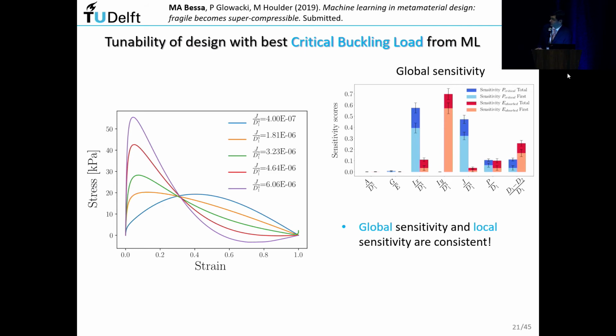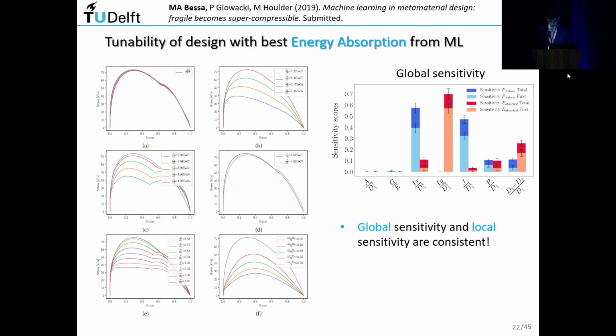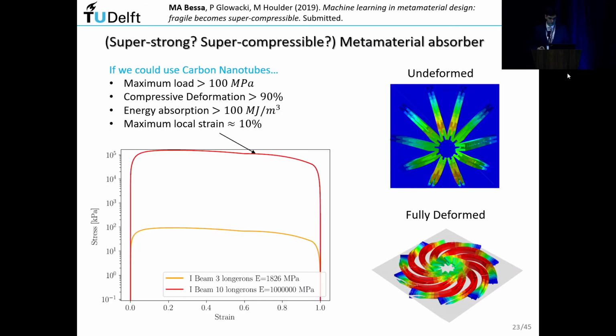You see here that it says that it's very sensitive, the buckling load, to the torsion constant, but not the energy absorption, which is exactly what these plots show afterwards as well. Okay, so there's more, but I'm going to skip this. Then one of my students got really excited, and he was like, well, Miguel, look, if we build this stuff with carbon nanotubes, we put an I-beam in the cross-section, we can get a super strong, super compressible material absorber with maximum load above 100 megapascal and incredible properties, okay, 90% compression and so on.